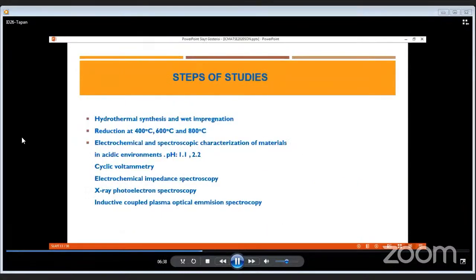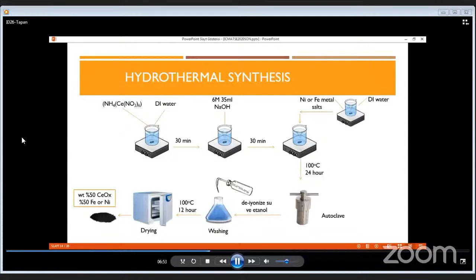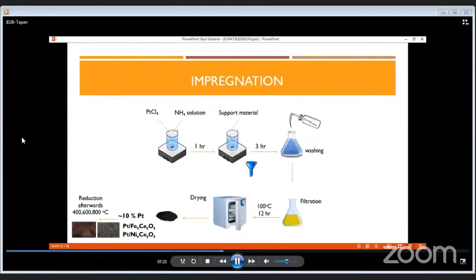Here in this slide, we present the steps of studies for development of hydrogen evolution catalysts. There is a preparation step which includes hydrothermal synthesis, wet impregnation, reduction of catalysts, and electrochemical and spectroscopic characterizations. In this study, in order to prepare the catalysts, hydrothermal and wet impregnation techniques were used. As seen in this figure, we prepare support material for 50% cerium and 50% metal taken as a basis. Then the other steps are hydrothermal synthesis and then washing and drying in the oven. After hydrothermal synthesis, as a second step, the wet impregnation step was applied. And then the reduction steps were applied at 400 degrees, 600 degrees, and 800 degrees.